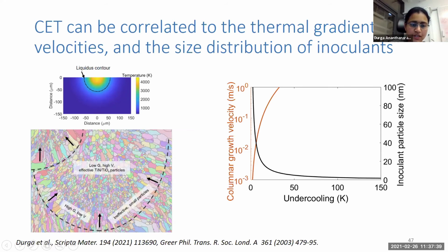In the case where we have very low velocity here, we can also calculate the columnar growth velocity by the methods I showed before. So here, if we have very low velocity, then the undercooling required for columnar growth is very low. So if we want our equiaxed grains to form here, we should add big enough particles that have even lower undercooling than this value for it to be effective. In the middle of the melt pool, we have higher velocities, so the undercooling for columnar growth is actually higher. But if we have particles in the right size range, then they have lower undercooling and they take over. So this kind of explains what we see here.